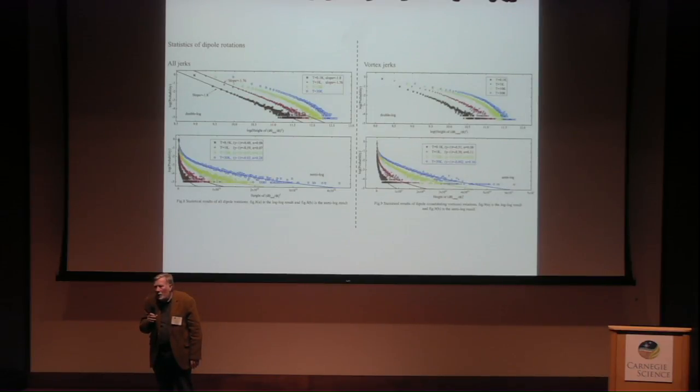But if you go to the walls only. Well, we assume it's a similar thing, because the walls are about 2 to 3 nanometers thick. So they're not just one atomic layer, it's 5 atomic layers. It's still very tiny. There's a big discussion on that, and the Russians argued that in truly two-dimensional you can't have it, but if you look at Kosterlitz-Thouless, you know you can. So I don't know, but the best bet right now is real space pairing. There's no evidence for BCS.